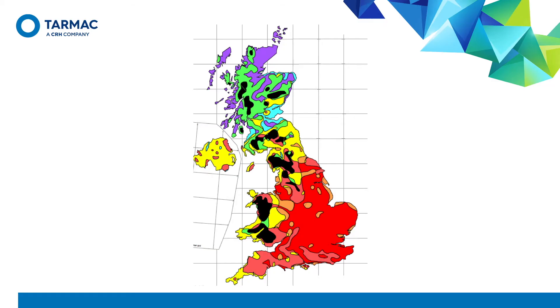The hydraulic design of a SUDS pavement is a specialist area and needs decisions about the design storm event — how much rain falls and how quickly — as well as knowledge of the permeability of the soil underlying a site. Clearly, if a site is on really dense clay then it isn't going to allow much water to soak away into the subgrade. The hydraulic designer needs to know the capacity of the granular reservoir layer. A well-designed and controlled GRL can be conservatively taken as 30 percent void space. There are generic open-graded stone specifications but sources might not have had the voidage determined, so it's advisable to stick with proprietary GRLs if possible.